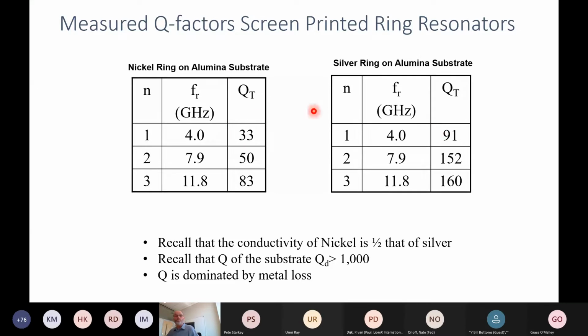You can note then the total Q here for the ring resonator is substantially lower than the Q of the dielectric. Remember, the Q of the dielectric was 1400. So here we're at 33, 50, and 83 for the nickel. And for the silver, we're at 90, 152, and 160. And you can start seeing, remember that the nickel conductivity is half of that of silver. So basically, we can see here the Q value of the nickel ring resonator is half of that of the silver. So that's really interesting.